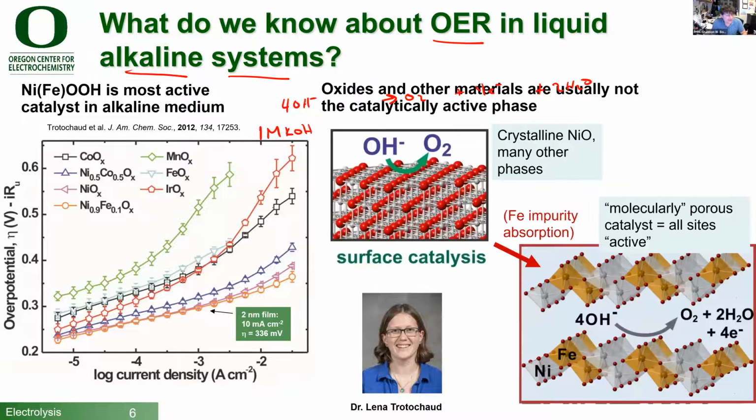The most active catalysts are not actually metal oxides. So if you have something like nickel oxide or cobalt oxide, you might have in your head a picture of the catalyst with some crystalline structure. It's a nanoparticle. But over time, it converts. And so it converts to these so-called layered double hydroxide structures. And the domain size of this ordered domain can be variable.